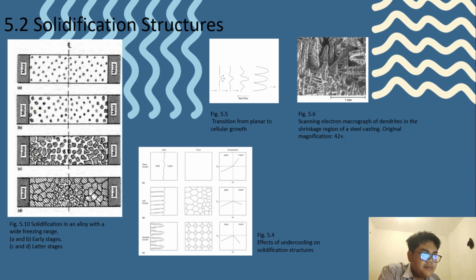The planar surface becomes unstable because any part of the interface that grows ahead of the remainder enters a region in the liquid that is at lower temperature. The initial spikes that form remain isolated at first because as they grow by solidification, they release their latent heat of fusion into the adjacent liquid, causing a localized increase in the temperature. Consequently, parallel spikes of almost equal spacing advance into the liquid. And on figure 5.6, we have a scanning electron micrograph of dendrites in the shrinkage region of a steel casting. Original magnification is 42 times.